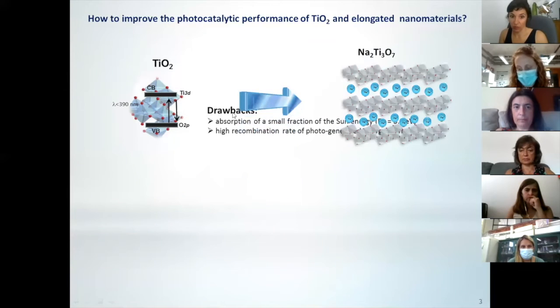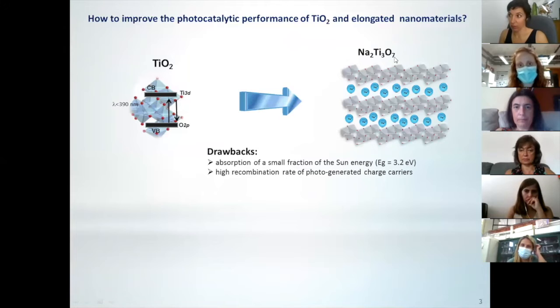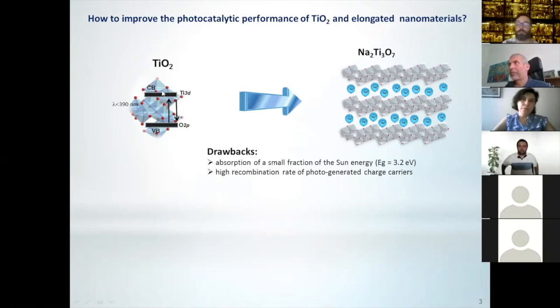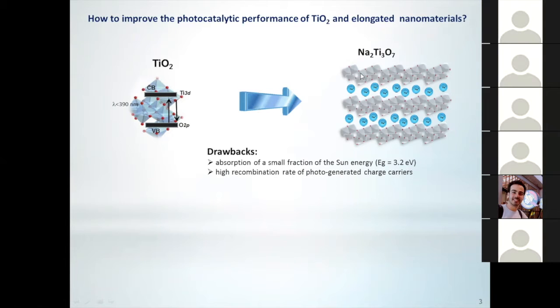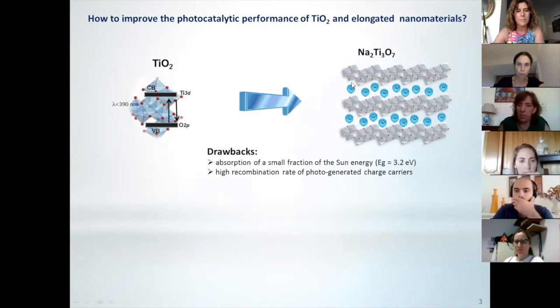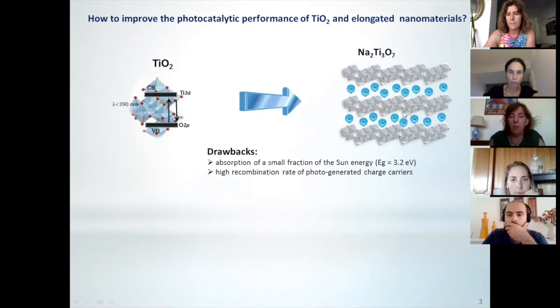Because of that, we propose the use of Titanate elongated nanostructures. Why? Well, they are very similar from the structural point of view. We also have the TiO6 octahedra, like in TiO2, but in this case, they have a layer structure, so we have a higher surface area. And we also have this sodium plus between these layers that gives us the opportunity to change these ions for different ones and try to play with properties of this material.